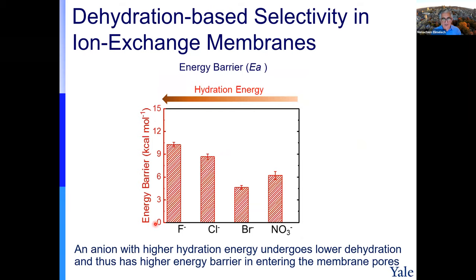This is the energy barrier for transport for fluoride, chloride, bromide, and nitrate, all as sodium salts, through an anion exchange membrane. We see that the energy barrier for fluoride is the highest. And why is it the highest? Because it has the highest hydration energy. Fluoride has the smallest ionic radius, so you need more energy to take the water molecules out. So it's very difficult to dehydrate compared to bromide. Let's not talk about nitrate, because nitrate is not spherical, it's a different shape, and the shape plays a very important role, and I will not talk about it.